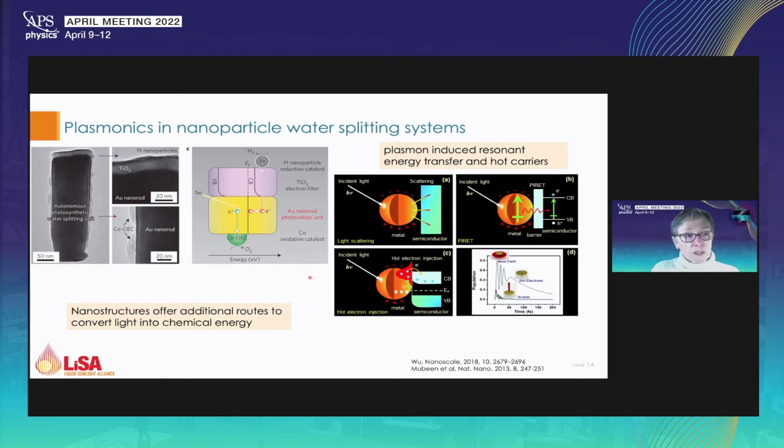But we can go a little further even and think about plasmonics, because one of the interesting things about nanoparticles is that they have plasmon transitions at various wavelengths, which is what gives the solutions their colors. And one of the things that has been done is to take advantage of that to build a highly miniaturized solar water splitting system, which consists of a gold nanorod, which is right here, that has a cobalt oxide catalyst, which is on the side, and platinum separated by a layer here, TiO2, and then platinum nanoparticles on the top.